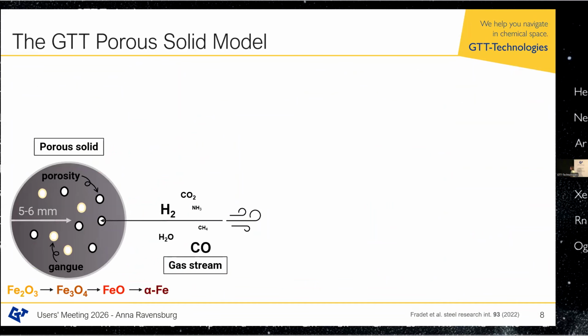But based on all of this work, we have tried to come up with our own model, the GTT porous solid model that is based on the work of Fradet et al. from the DLR. And we have tried to extend this porous solid model. What we have been doing is that you take the pellet and assume it's a porous solid, and then you have a gas flowing through this porous solid. A gas stream that can have different compositions, it can have H2 and CO in different mixtures. And then you reduce your Fe2O3 over these 3 stages to alpha iron.